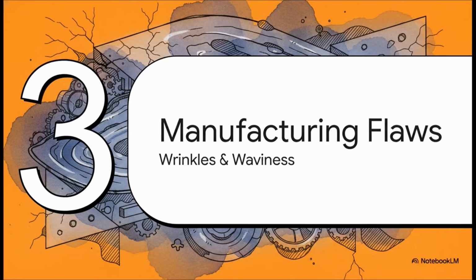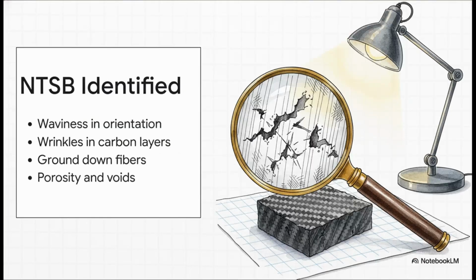Which brings us to Part 3, Manufacturing Flaws and Wrinkles. When the National Transportation Safety Board did their forensic analysis on the trimmed ends of the Titan's hull, basically the leftover pieces from fabrication, what they found was just a litany of terrifying anomalies. We're talking waviness in the fiber orientation, deep wrinkles in the carbon layers, areas where fibers had been aggressively ground down, and extensive porosity, meaning tiny hidden holes or voids.